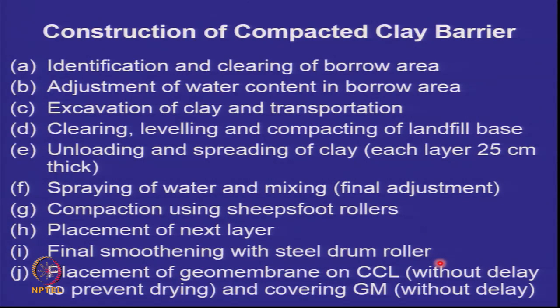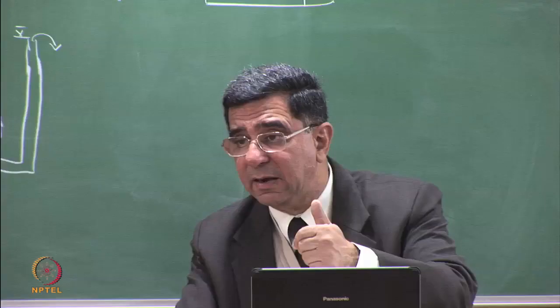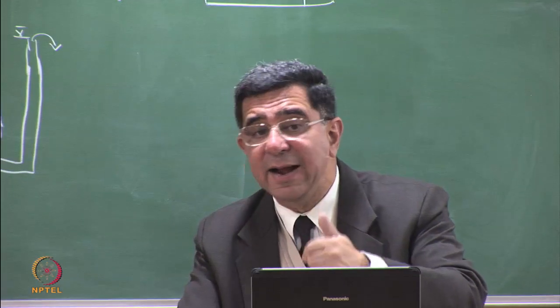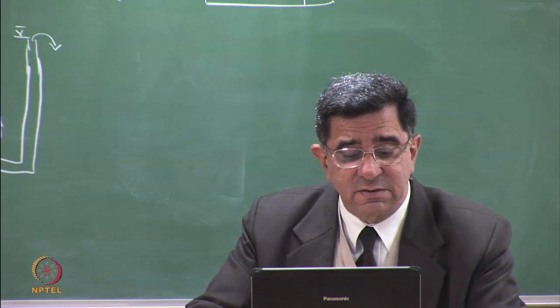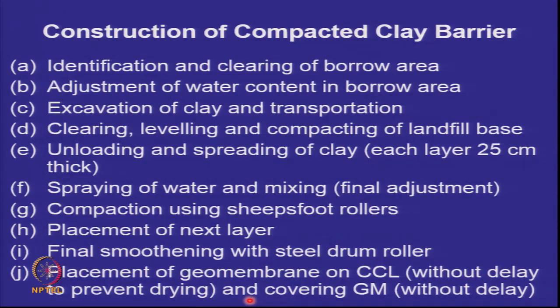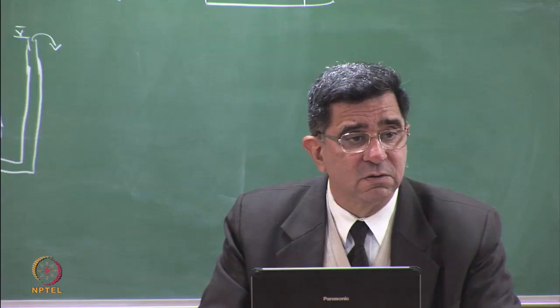And then as soon as the final smoothing is done, we have to place the geomembrane on the compacted clay liner so that the liner clay does not become dry and desiccate and you don't get shrinkage cracks. And further, we should cover the geomembrane without delay with a protector so that no damage takes place to it.